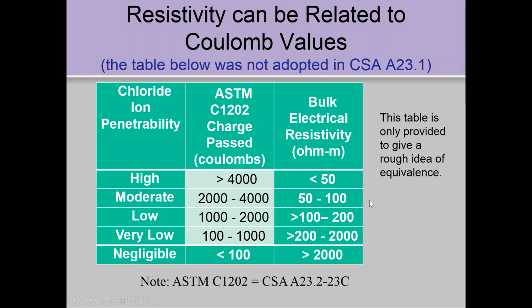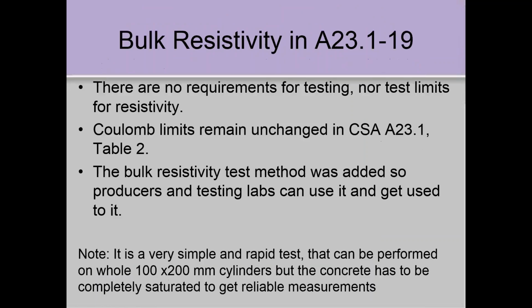We want people to do the test. A number of labs are doing the tests, so they do the comparative testing and get comfortable with it. So that's what I'm saying here. It's a simple test. You just have to have a completely saturated sample to get reliable results. If the concrete's not wet, concrete's a good resistor. If it's saturated, then you're measuring the electrical flow through the pores in the paste fraction of the concrete.